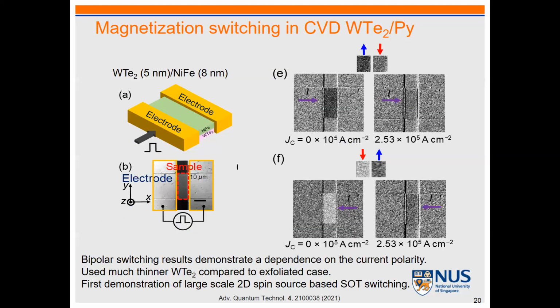So we tried to make Weyl semimetal, tungsten ditelluride, using CVD, because CVD is more CMOS friendly and large area wafer scale. So this is wafer scale fabrication. Then we can do the same thing with the permalloy on top. But still, this is an in-plane magnet. But we show you can nicely switch black to white to black with a reasonable charge current. And this is the first demo of large scale 2D spin source based switching. But again, from here we have to go to PMA, field-free switching.